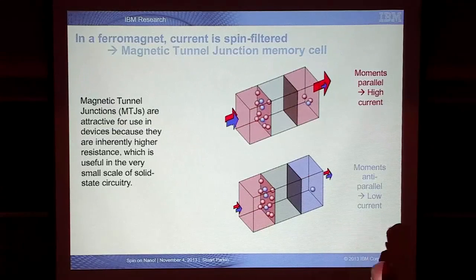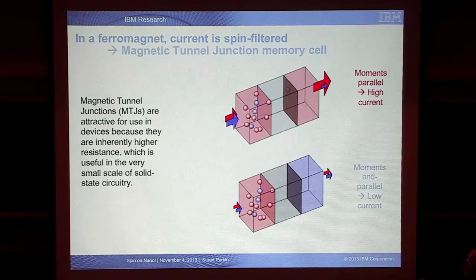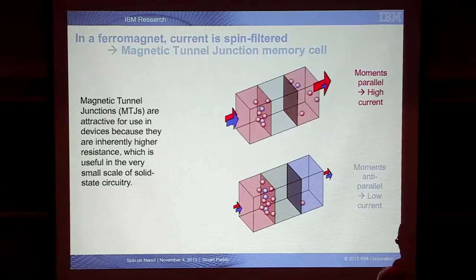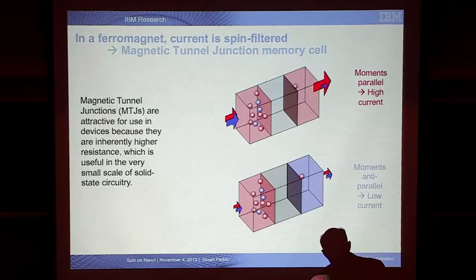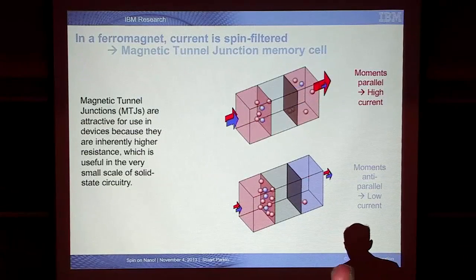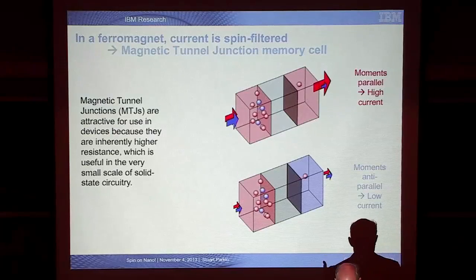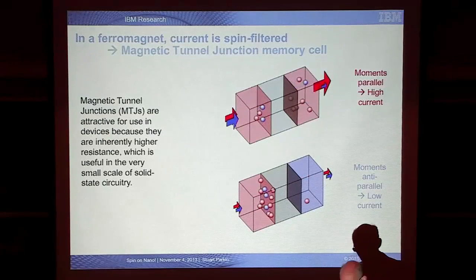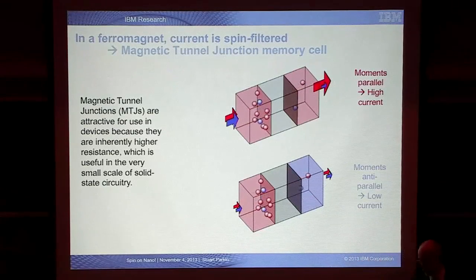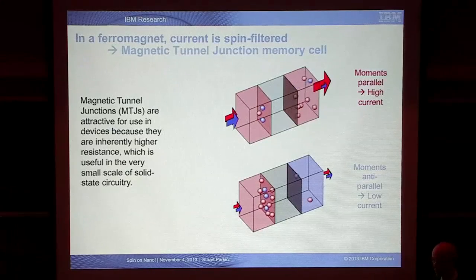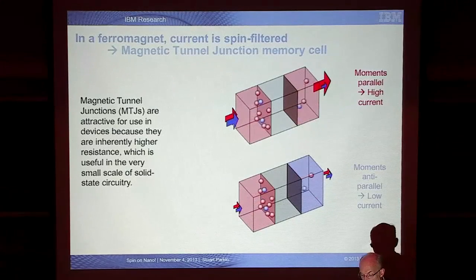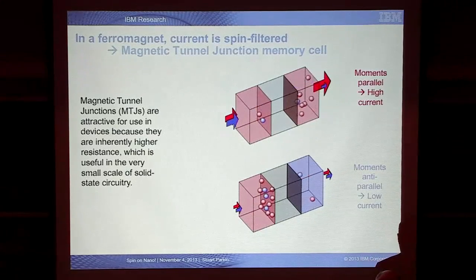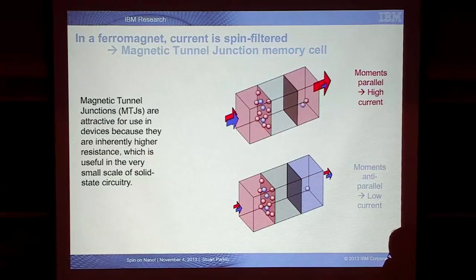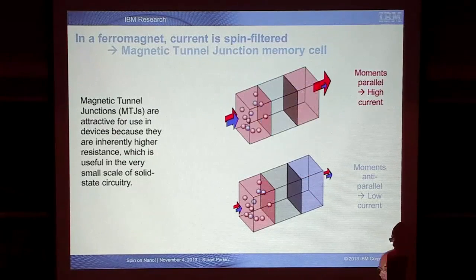So essentially now, by changing again the relative orientation of these layers from parallel to antiparallel, we can change the tunneling current. But unlike the metallic spin valves, where we had the copper separating these magnetic layers, the results are much bigger. And instead of changing the resistance, as I showed you in a multi-layered structure, by a factor of 2, or in a spin valve, where the change in resistance is only 10%, that's all that is needed to make this extremely sensitive detector of magnetic fields.